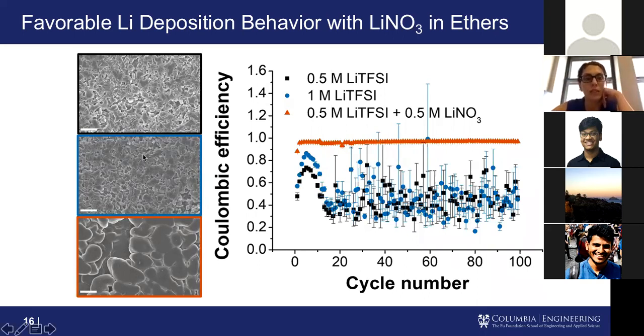What the black and the blue squares and data points here are showing is an ether-based solvent with a standard lithium salt. When we look at the Coulombic efficiency as a function of cycle number, it seems pretty good to start off with, but then it quickly falls off and becomes very scattered because the battery is likely starting to short circuit. The performance is not very good. If we take a look at the SEM images over here, we again see these high surface area structures. So it tells us that we still have something pretty unfavorable in our SEI that's causing these dendritic structures to form on the surface of our lithium metal.